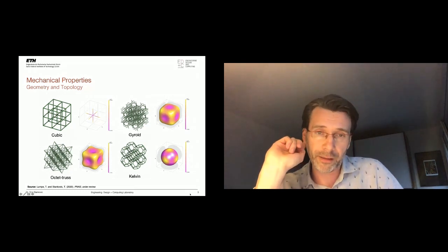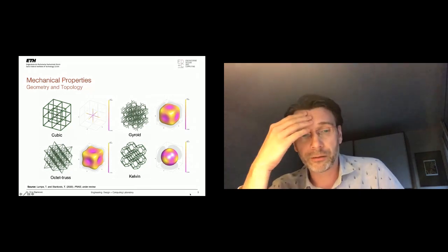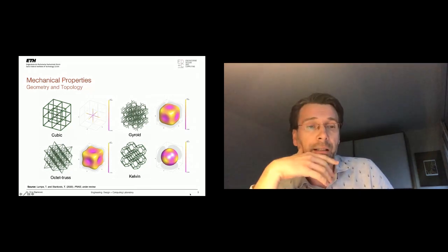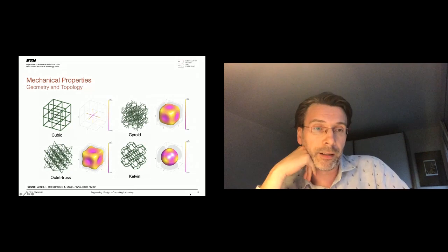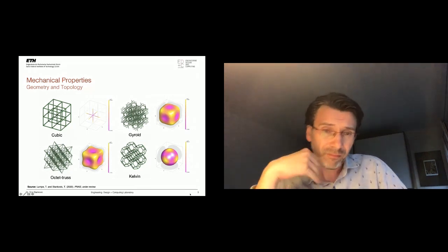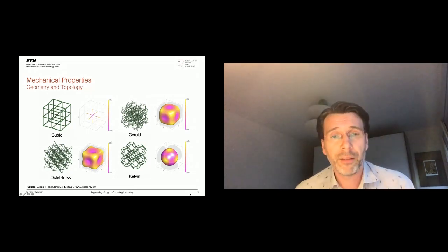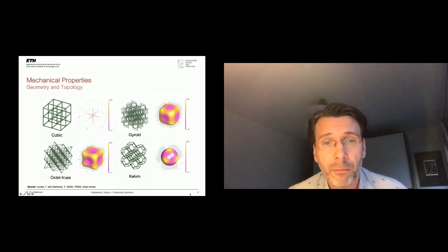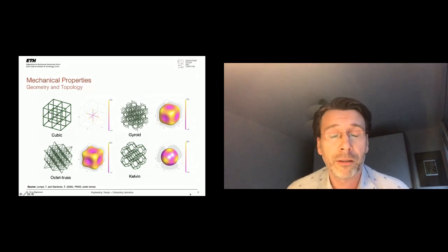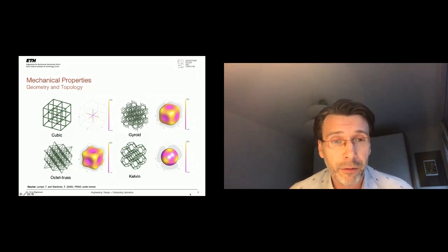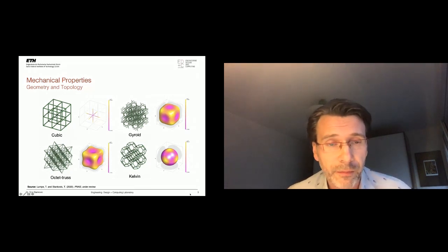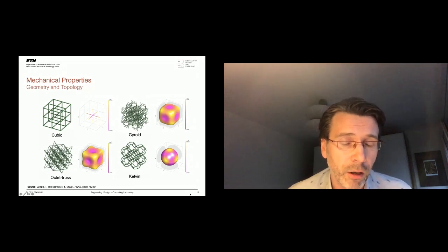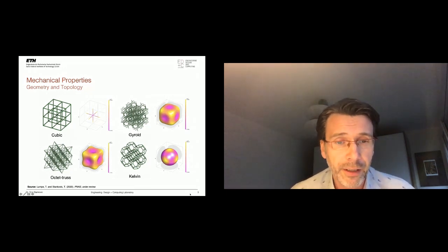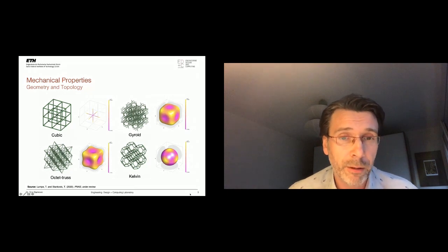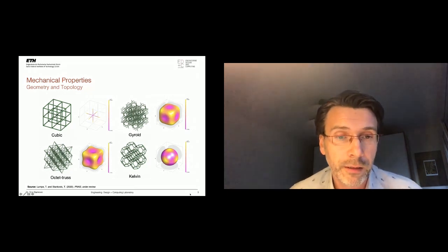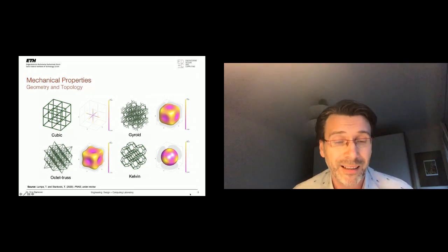I took this image from one paper about ultralight, ultra-stiff mechanical metamaterials, and this chart shows the Young's modulus over density plot. What is interesting is that, using architected materials, we are trying to combine properties that normally don't appear at the same time with conventional materials. If you take, for instance, the red squares or hollow squares plot, you can see that there is a certain range of properties of material that is almost as stiff as metal, but at the same time significantly less dense.